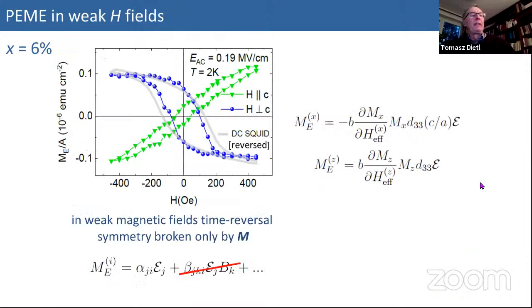And again, you see that in weak magnetic fields, you have opposite sign for this electric field-induced magnetization. For the easy axis, this magnetization has the opposite sign to that measured by SQUID, but a similar shape, while in the hard direction, we have a similar sign. And the same formula which I showed a second ago can be used, and now we understand that the external magnetic field is 0, this is kind of constant, and indeed we have opposite sign.